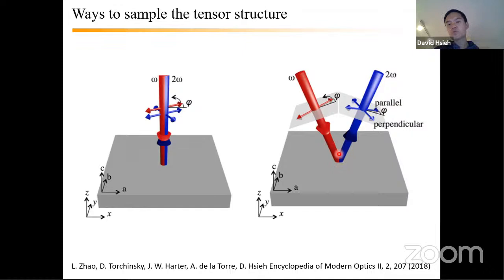And moreover, if you wanted to look at the rotational symmetries of the crystal, let's say about the C-axis, you can intuit to yourself that to do that, you'd really want to rotate the crystal, right? Here, any rotational symmetry that you get from simply rotating the polarization is going to have the symmetries of the optic itself, not the crystal.